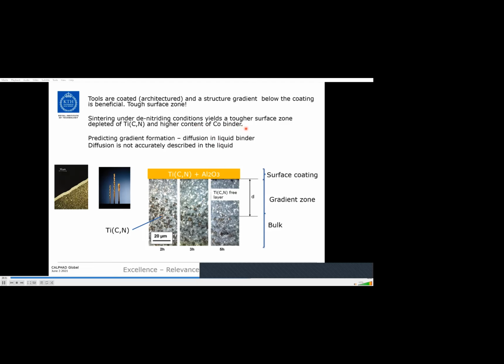And what would you like to do? Well, you would like to predict the gradient formation. Now, this gradient formation occurs during the liquid phase sintering. The problem is that diffusion in liquid is not very well described. Here is a type of microstructure we are talking about. We have a surface coating, and here we have the gradient zone, and this is now treated for various times. So in this layer, there are no cubic carbonitrides. Here, on the other hand, we have the dark phases, or the cubic carbonitrides. So this is a gradient zone.